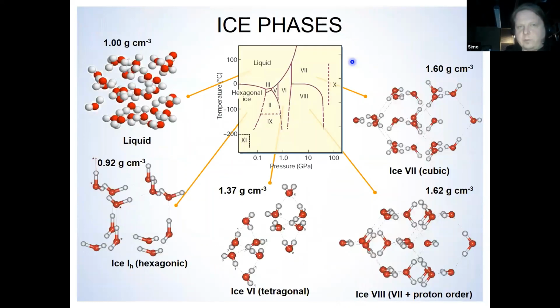So I just wanted to mention that we wanted to do a systematic study of known structures that have this water molecular network, and we of course can access different ice phases. So condensed phases of water, there are numerous different crystalline and amorphous phases, and this shows a part of the phase diagram of water. If you compress liquid water at room temperature, you can go to the ice phase called ice 6. These are labeled with numbers in basically ascending order. So there's ice 6, which turns into ice 7. Ice 6 has a tetragonal structure. Ice 7 is cubic. And then if you lower the temperature from ice 7, you can go to ice 8, which is otherwise the same as ice 7, but it has a full proton order, while the others are proton disordered.